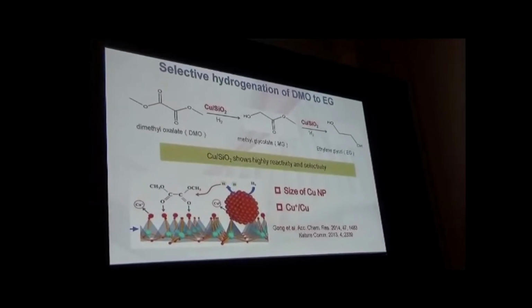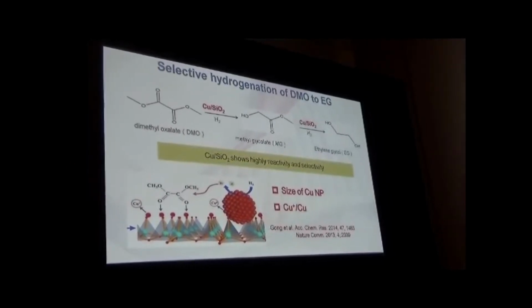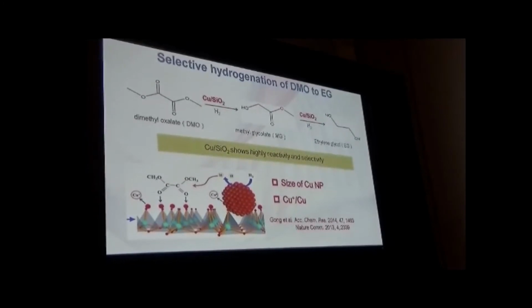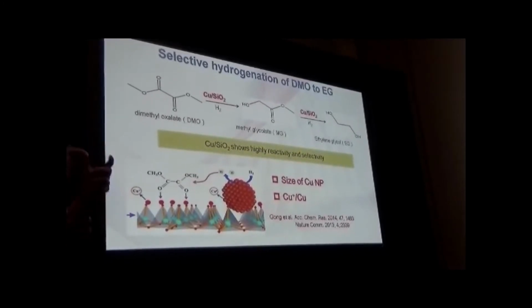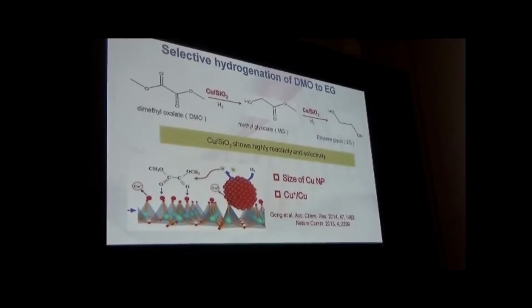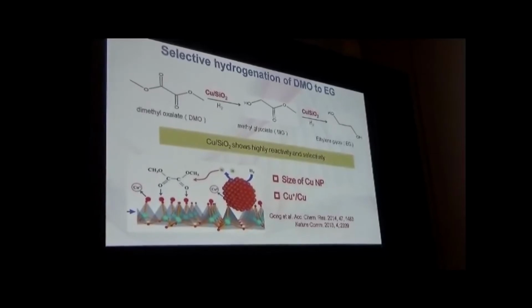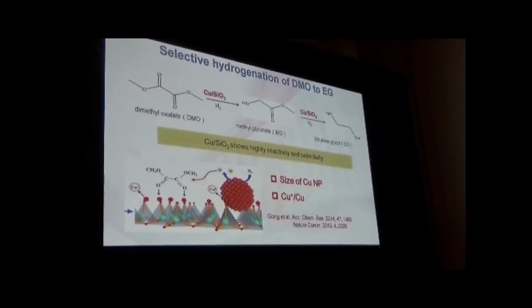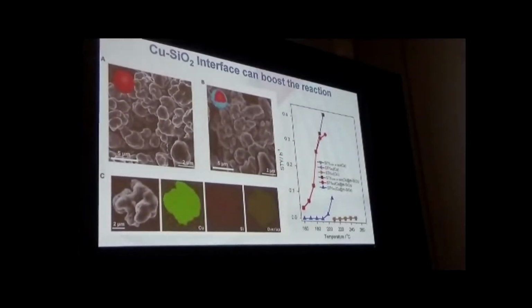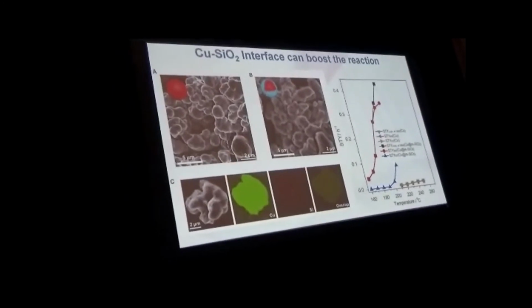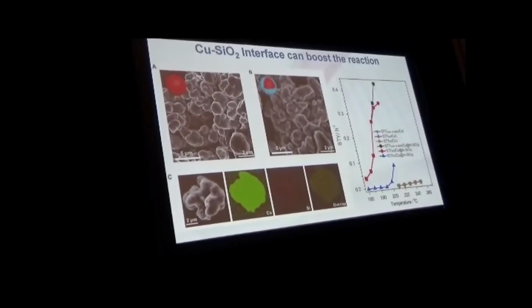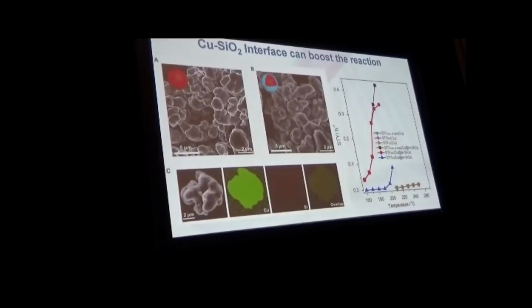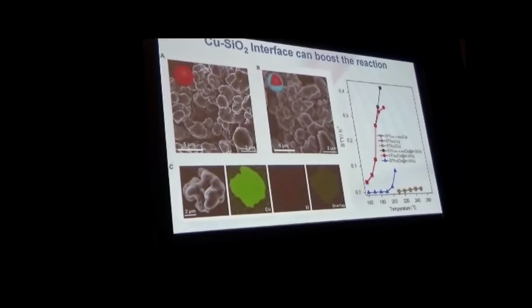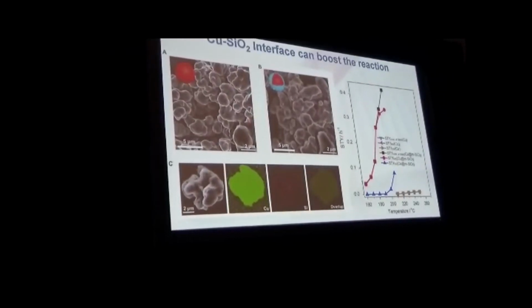But as we know, when we reduce the size of the copper, we not only enhance the nano effect, but also enhance the interface effect. How to decompose the nano effect and interface effect? Here, we can approach it from another direction. We can synthesize copper powder at the micro scale. Because it's micro scale, there are no nanoparticles. In this case, there is no nano effect.